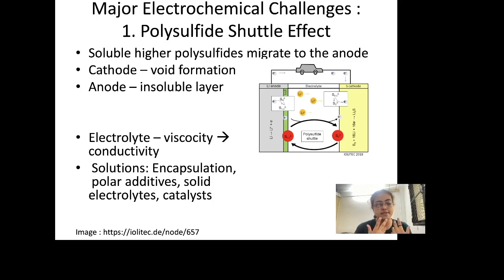And thirdly, we have the electrolyte. Because of these higher order sulfides getting dissolved into the electrolyte, there is an increase in viscosity of the electrolyte, which in turn reduces the conductivity of the electrolyte, and that is also very detrimental to the battery capacity. And you can really visualize the effect from the picture I have added here from this website.